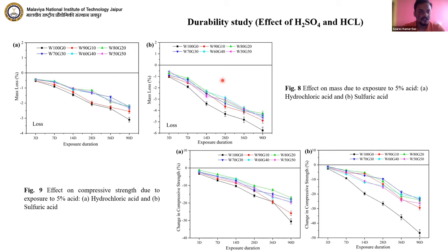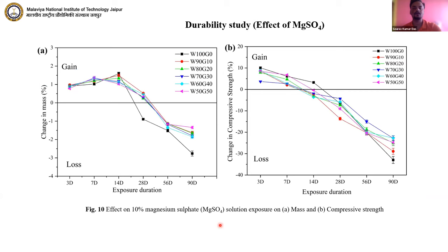Coming to the durability, you can see that our waste cement concrete has a huge reduction both in mass and in compressive strength. This black line is the 100% waste cement concrete. Anywhere you utilize glass waste, it increases the durability in terms of mass and compressive strength retainment. For sulfate attack, things remain the same, but there is an initial gain in the mass and in the strength up to 7-14 days. Then it gets reduced, and the experiment has been conducted up to 90 days.